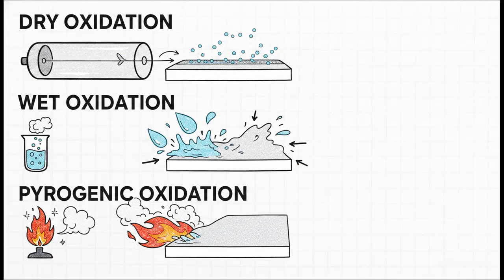Inside those red-hot quartz tubes, engineers manipulate the environment using three distinct methods. We've got dry oxidation, wet oxidation, or pyrogenic oxidation. Dry oxidation uses pure oxygen gas. It's a pretty slow process, but it creates a highly dense, incredibly high-quality oxide layer that is just perfect for delicate gate oxides. Wet oxidation, on the other hand, uses the water vapor from that bubbler vessel. It's much faster because the hydrogen and oxygen molecules diffuse through the silicon more rapidly, which makes it great for thicker, structural masking layers. Finally, pyrogenic oxidation actually combusts hydrogen and oxygen directly inside the tube to create an ultra-pure steam, giving you a great combination of speed and high purity.